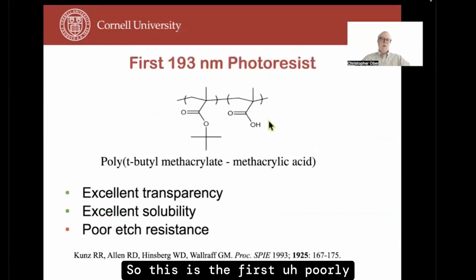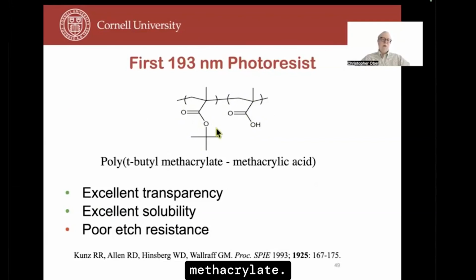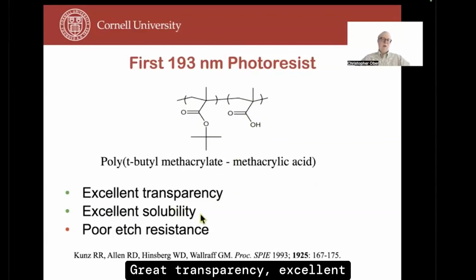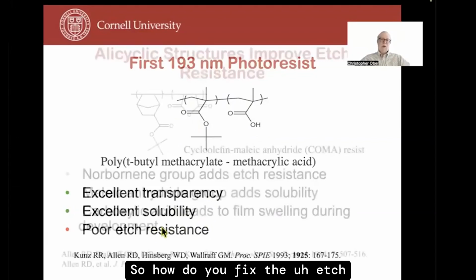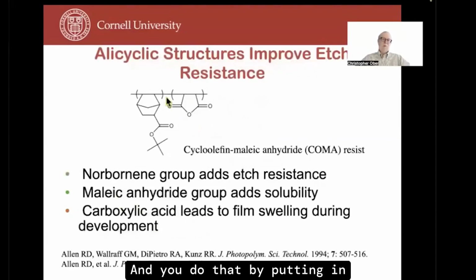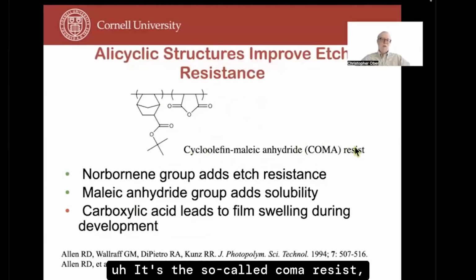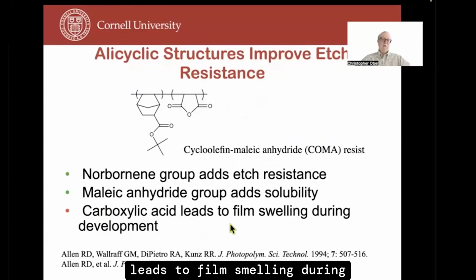So this is the first poorly etch-resistant 193 nanometer resist, but it was based on methacrylic acid and T-butyl methacrylate. Great transparency, excellent solubility. So how do you fix the etch resistance? You do that by putting in alicyclic structures. So this is one composition that was looked at. It's the so-called COMA resist, but the presence of carboxylic acids, too many carboxylic acids, leads to film swelling during development. And so you can think of it as a transitional structure.